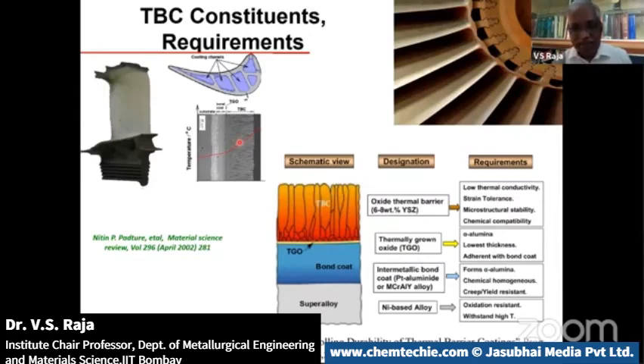How do you tolerate the strain? You tolerate the strain by growing these oxides in a columnar manner. Please look at this. There is aligned growth of these oxides, and because of this aligned growth, when they start moving like that, the strain is taken care of. They don't really break. But there are some issues here, because these grains allow the corrosive liquid to go inside. There are some problems.